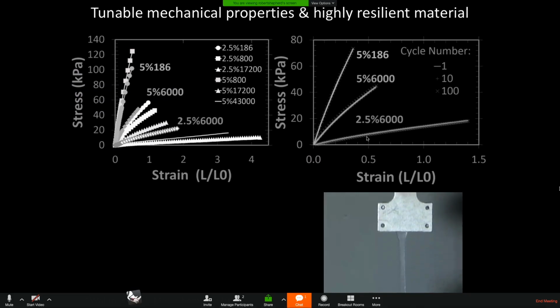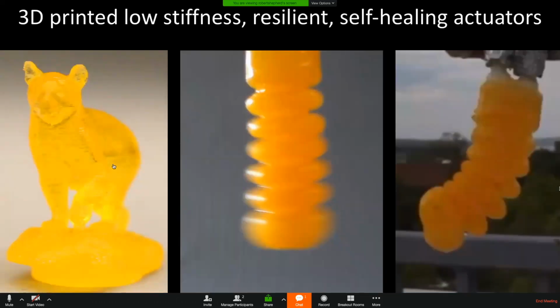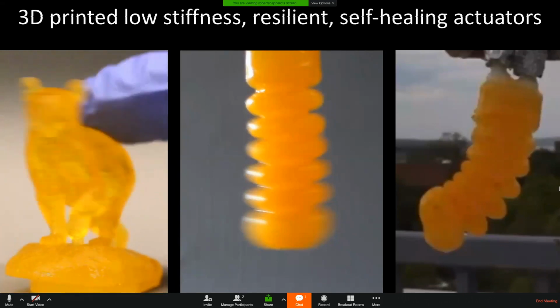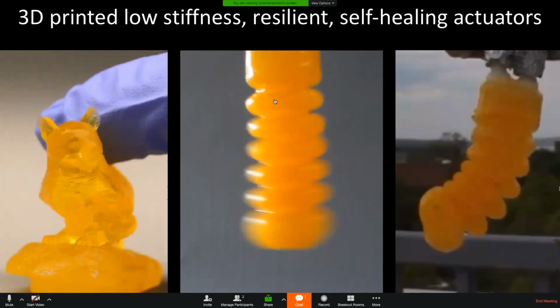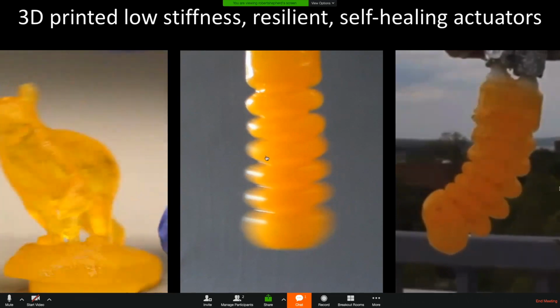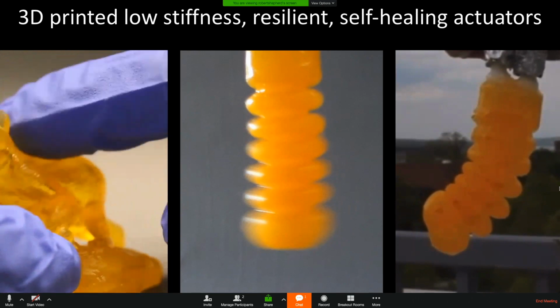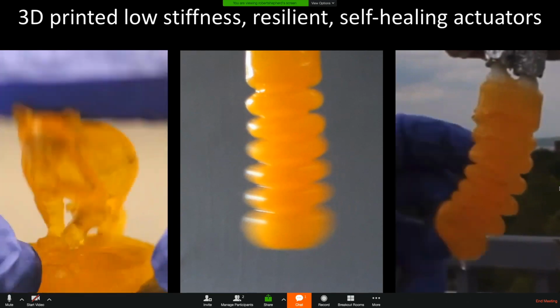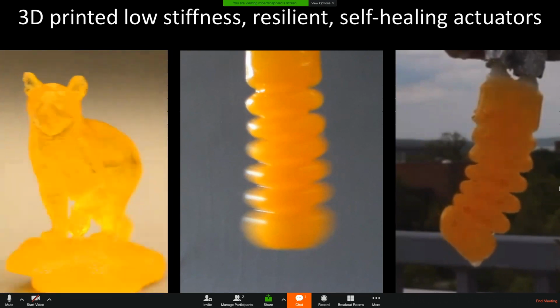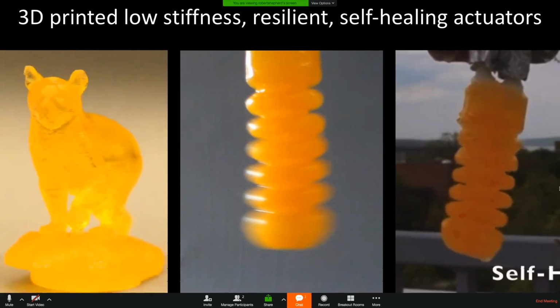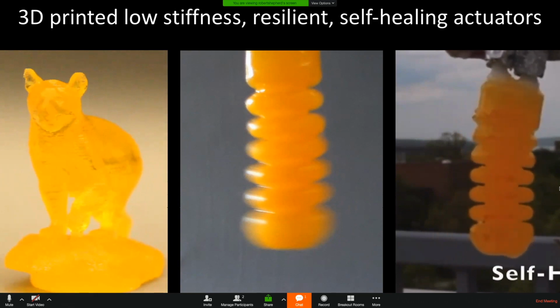But the most important part is that it is very soft, sub 100 kilopascals, and it's very resilient. So we can cycle it hundreds of times without it failing or without it even changing its stress strain profile. Using this material, we could print extremely soft actuators and figures. This video isn't playing, but anyway, they do work as actuators and they're very soft, and they have an additional benefit that if we keep the unreacted photochemistry on the inside of the actuator and it gets pierced and leaks, then the sunlight can cure it and self-heal it.